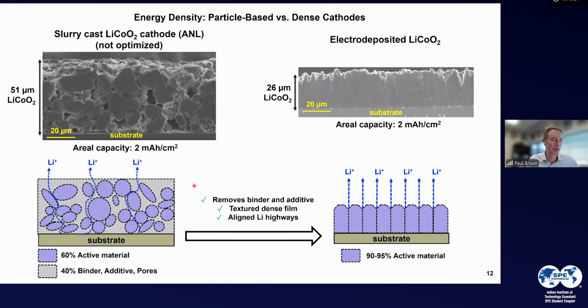So you might ask from an engineering standpoint, what is the advantage? If one looks at a slurry cast lithium cobalt oxide cathode, when it's 50 microns thick, it has a capacity of about 2 milliamp hour per square centimeter. In the electrodeposited material, when it's 26 microns thick, it has the same areal capacity. So the thickness is reduced by almost a factor of 2.